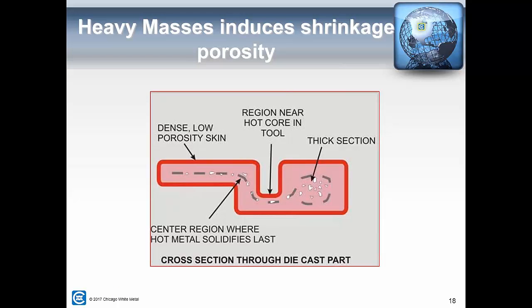So this slide here shows kind of what the results of a thick section can be. The middle line right there is showing what is basically the last part of that wall thickness to fill. So in some of these outside corners right here, you can see this is actually surrounded by colder steel. So this corner is actually going to cool faster than this inside corner. And then similarly in this section right here, where we have a thicker section, die castings will freeze from this outer wall and then pull material from the inside and freeze from the outside in terms of the actual part.